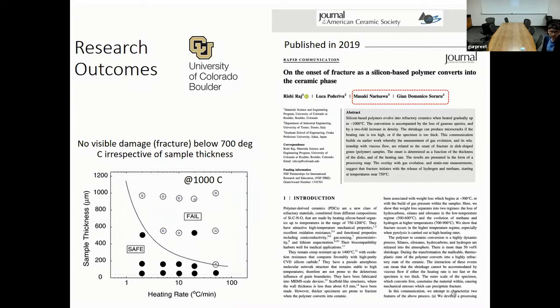They also noticed that samples pyrolyzed at 700 degrees C did not fail irrespective of the thickness; they all survive a 700 degree pyrolysis temperature. They attribute this behavior to the organic matter that comes out at different temperatures. Specimens processed at 700 degrees C survived because they did not observe evolution of methane or larger molecules below that temperature. Methane along with hydrogen starts to come out at 700 degrees C or higher, and that is perhaps the reason for failure of these thicker samples.